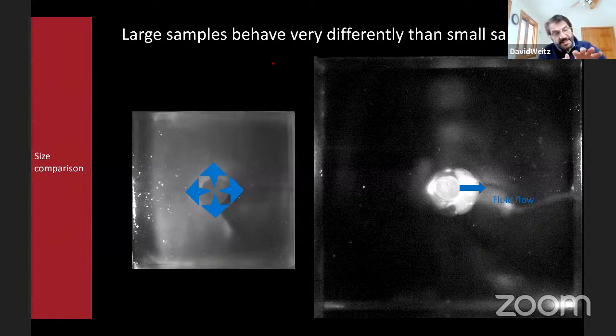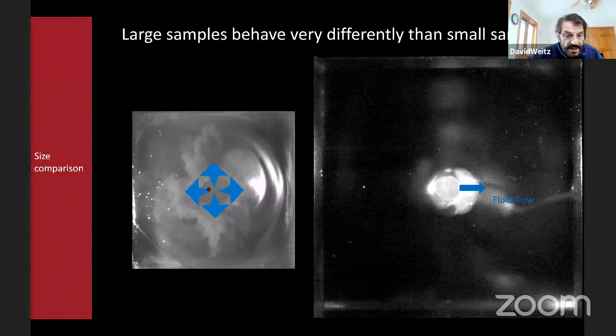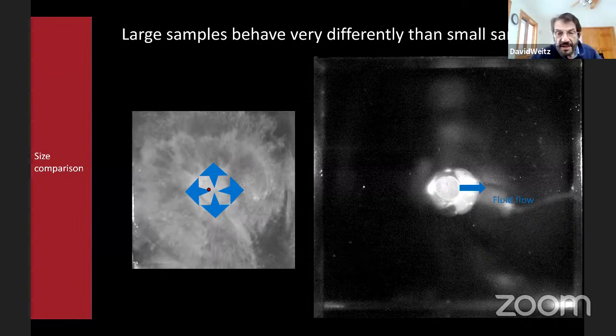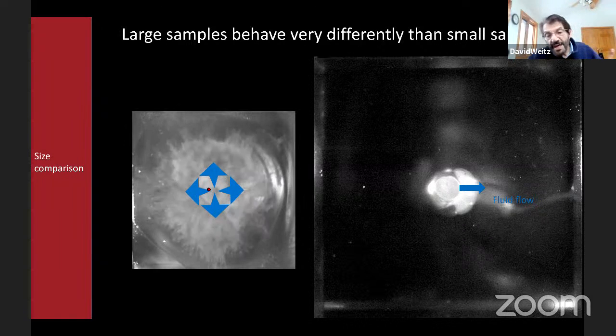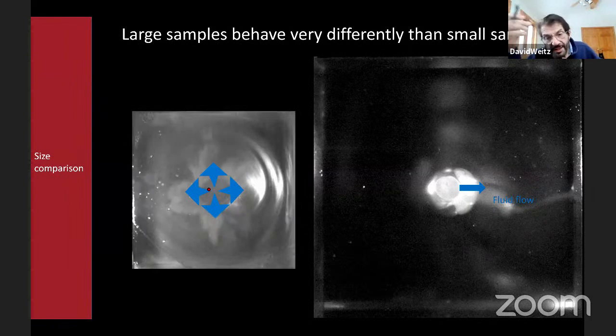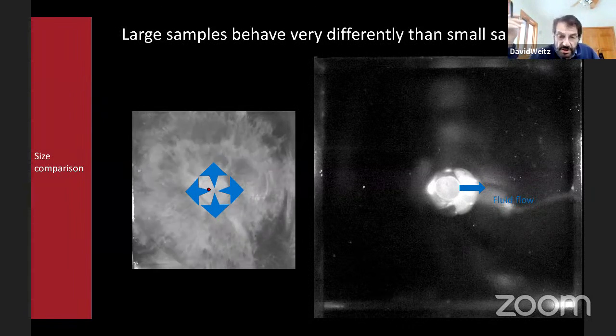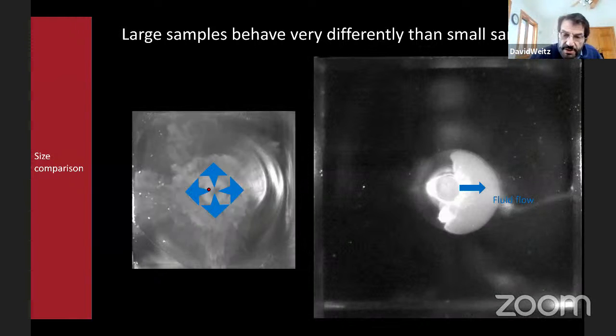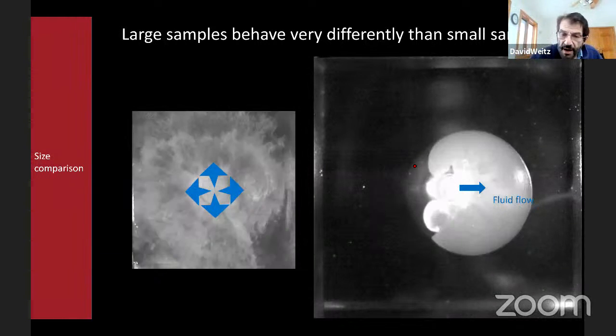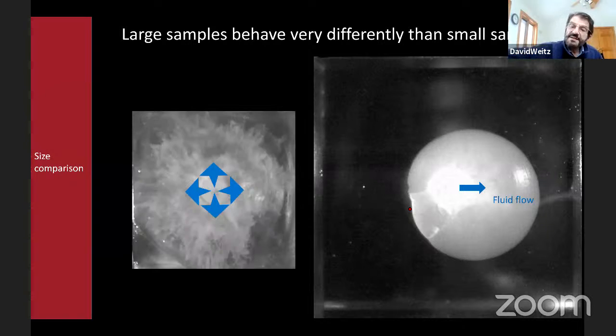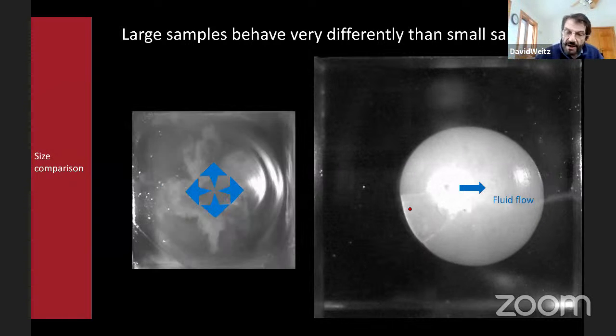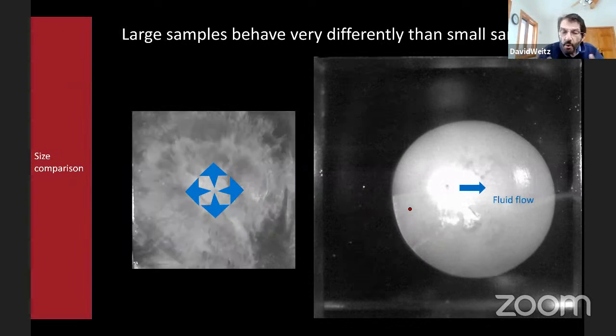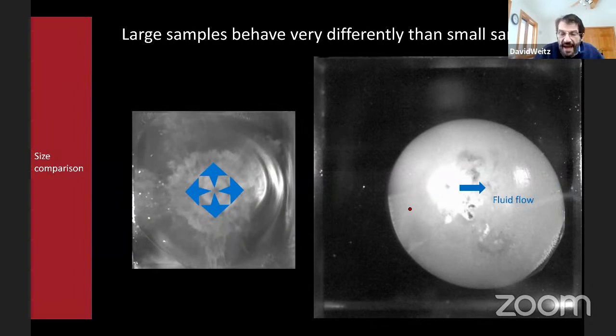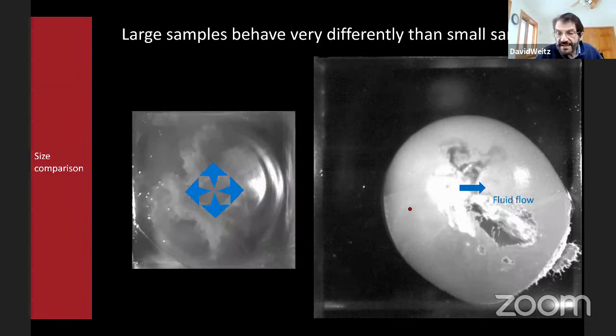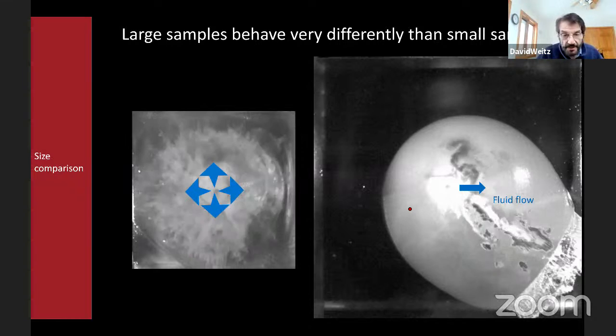Well, what's happening is that we're tearing the sample apart. It's the small sample. It's just being torn apart. So a simple thing is just to make the sample larger. Now, when you're 3D printing it, it's not so easy, but you can do that. And now what you see is you can get to the point where you get a fracture, but it doesn't tear the sample apart, and you have time to watch the fluid catch up to the fracture and understand something about the nature of the fracture.